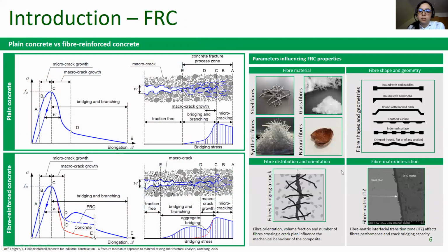However, the performance of a fiber-reinforced concrete is affected by different parameters. First of all, the fiber material. Both organic and inorganic fibers can be used as reinforcement in traditional concrete. For example, steel fibers can be used to improve the mechanical properties and in particular the flexural post-cracking behavior, while, for example, microsynthetic fibers can reduce shrinkage deformation. However, in addition to fiber material, also fiber shape and geometry, distribution and orientation, and especially the number of fibers crossing a crack can affect the performance of the fibers and the final properties of the composite.